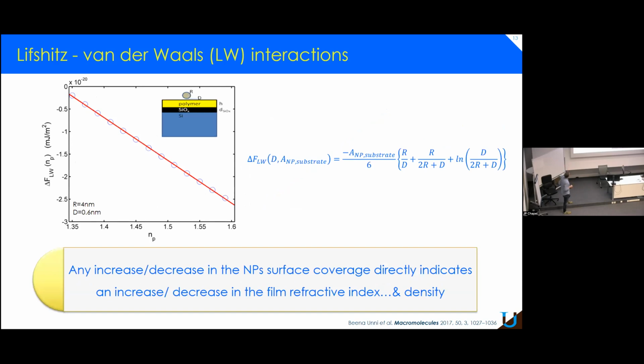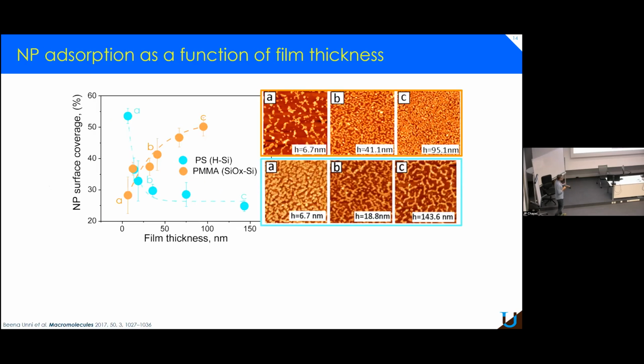This is typical interaction free energy, and this tells you that any increase or decrease in the nanoparticle surface coverage should directly indicate an increase or decrease of the film refractive index. And then relationship. And so actually it's what we did.